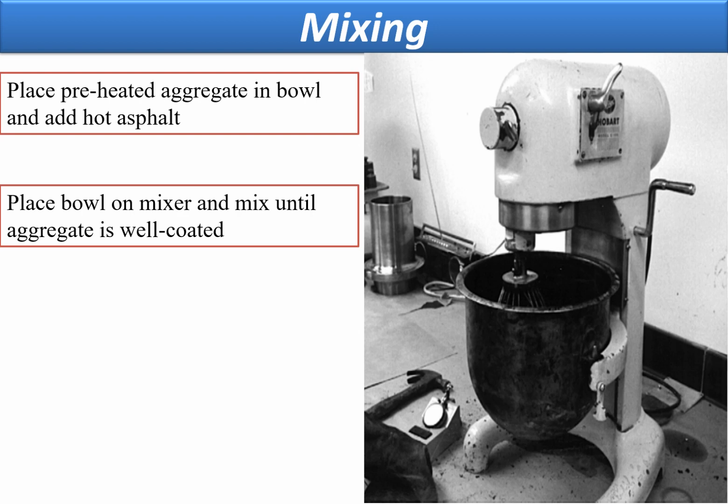mixes the mix completely. So in the absence of the bituminous mixture, one can do the pan mixing also, but the problem associated with pan mixing is you are not sure about the mixing quality, because the uniformity and the RPM of the mixing is difficult to maintain. But with experience, one sometimes makes sure that the mixing is being done properly, but the chances of overheating of a particular aggregate or a bituminous content is high when you do a manual mixing using a pan.